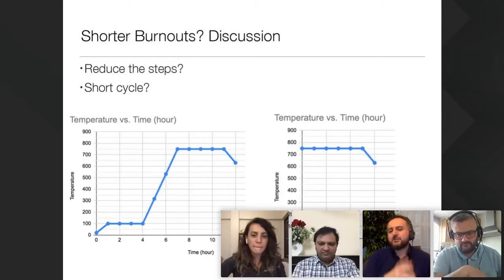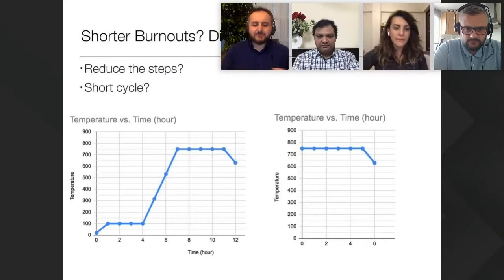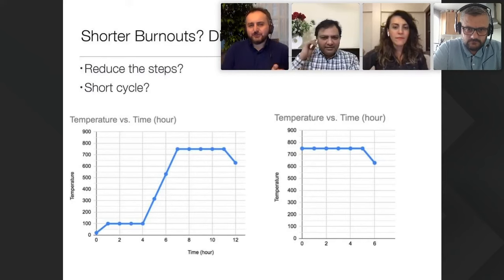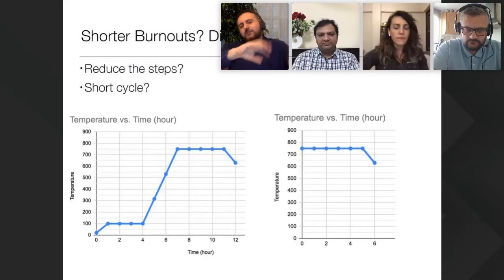Actually, this is a good one. We have an R&D department with an oven, and we do a lot of tests, and we did this actually. We put it up, down, sideways, and everything. Whatever you do, when you break the investment and open it, if the resin has the proper, let's say, one of our resins, you don't see anything. So whether you put it down, and the reason for that, I think, is because if we speak about resin...